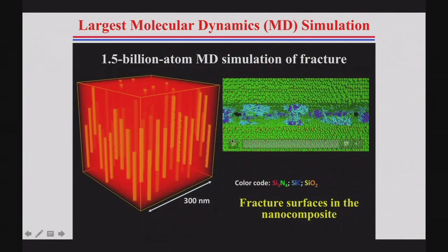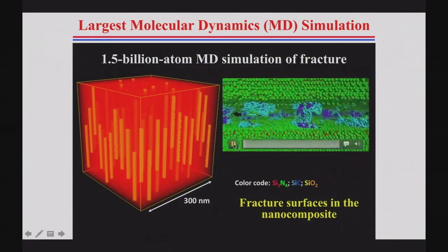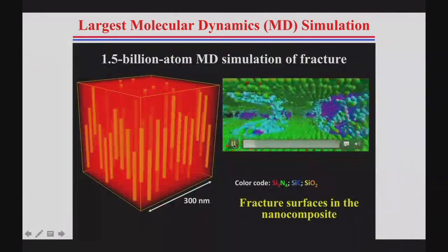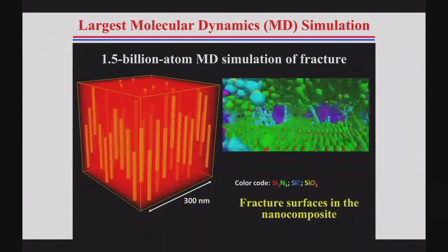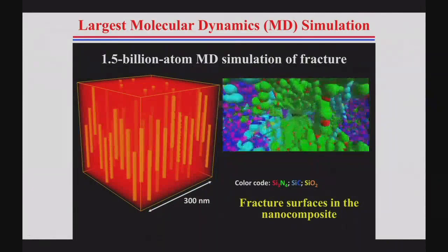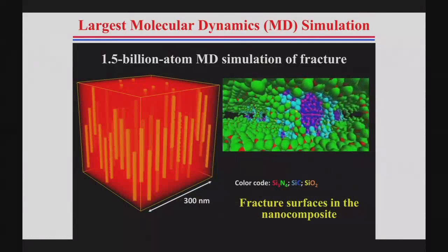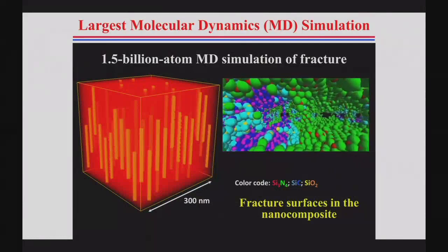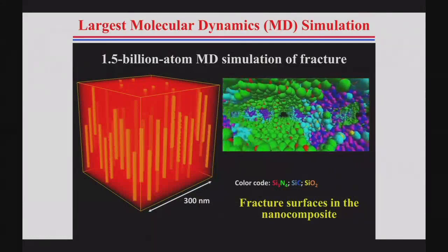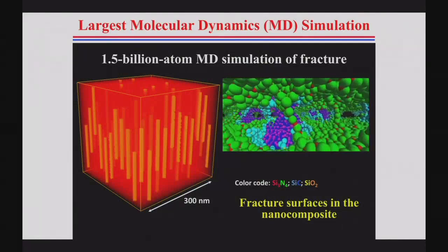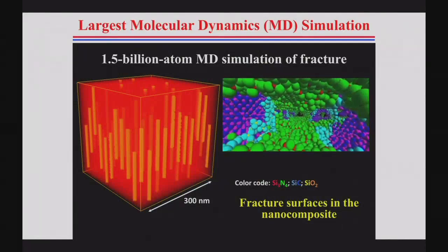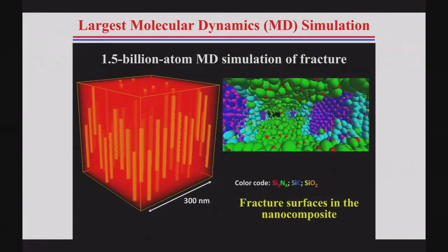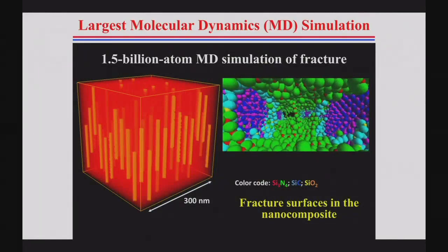And in this movie, you can see the reason why it is tough. The crack is propagating, and as you can see, the fibers are holding the material together. They're not letting it break. And so you can apply very, very large strains, and the material is still intact.